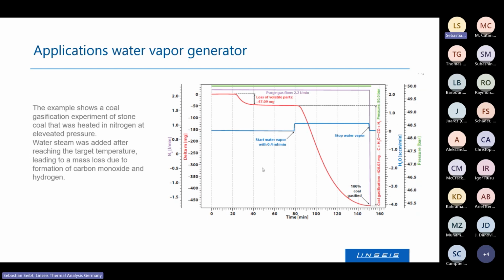So what was done here: the sample was heated up to a certain temperature. During heating, there was a little mass loss, which is the volatile components, like solvents or hydrocarbons that just burn off or evaporate at lower temperatures - that's what you lose anyway.